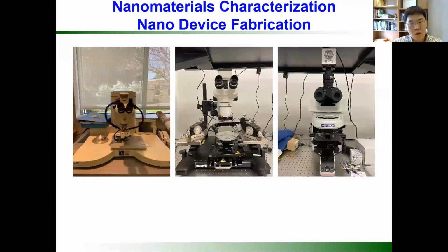In terms of the crystallinity, how high quality the hexagonally bonded carbon atoms we can create. We characterize the quality of the materials, and then we measure the conductivity and electrical properties of the material using probe stations. We also characterize optically, by looking at the material's properties using the scanning electron microscope or optical microscope. We first inspect the material's quality and structures at a micro or nanoscale. Here, using this optical microscope, we can see even the microscale structures. We also fabricate devices using the wire bonder that we have in our lab. We can make devices to use for nanobiosensors in bio applications, for example.